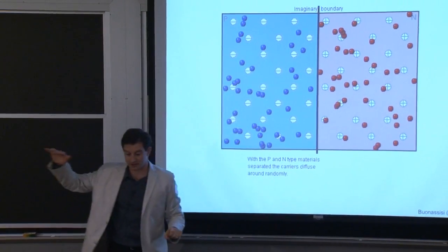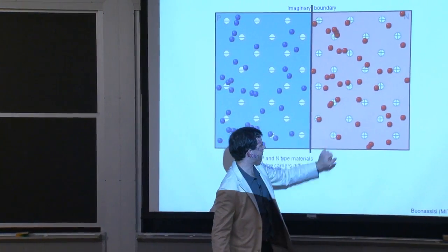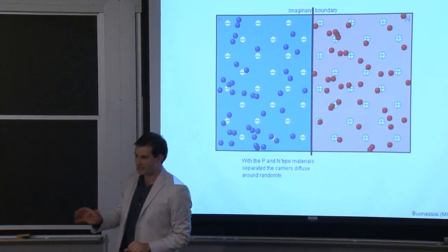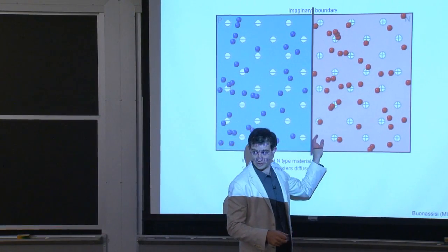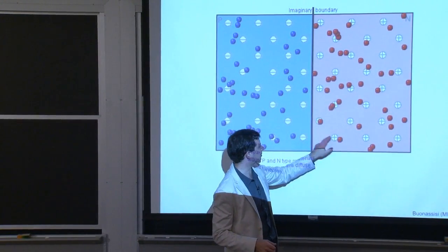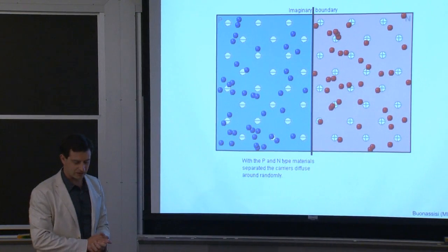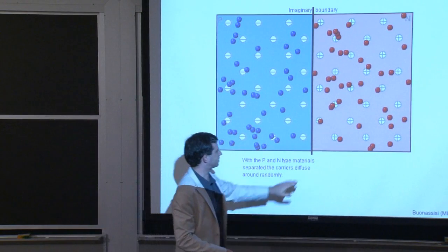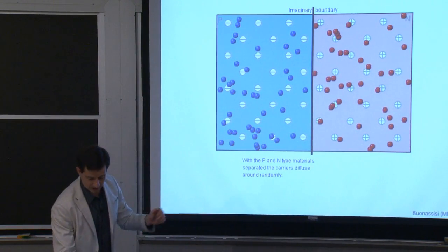They're in the conduction band. They're able to move. And because the binding energy to the phosphorus atoms is on the order of 10 meV, the thermal energy here at room temperature is enough to dissociate them and allow those electrons to move away from the phosphorus atom, thanks to the screening potential of the surrounding lattice and the fact that electrons inside a crystal can move more easily than in vacuum.